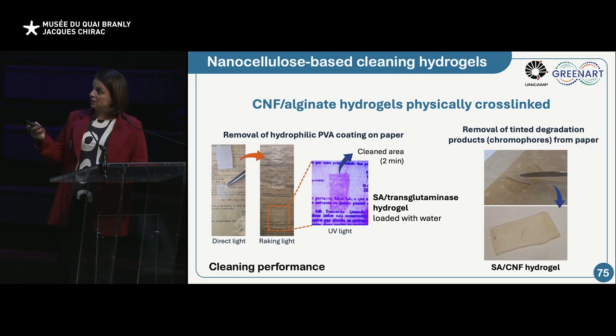This is the CNF alginate hydrogel. So I mentioned the alginate there behind. This is the removal of hydrophilic PVA coating on paper. So we have the gel applied here, another piece of gel here, and we can see here under UV light the area that was cleaned by the gel.